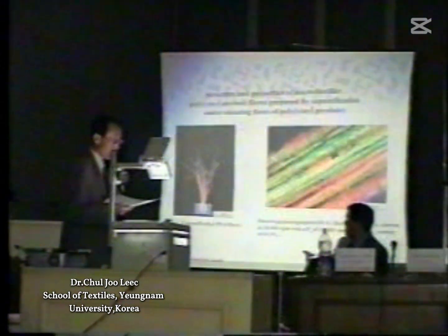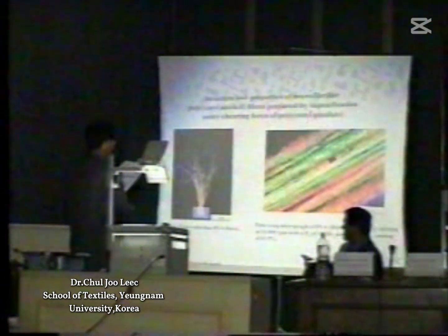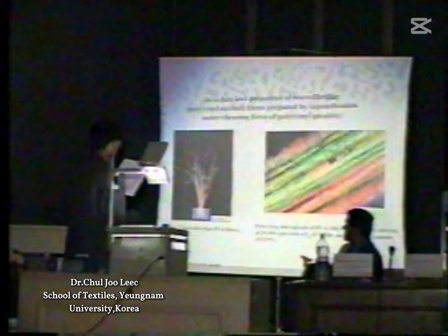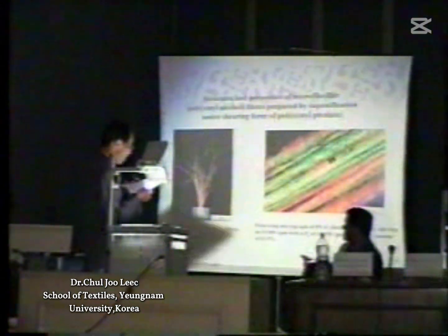I think many of you are now wondering what the fibrillars are. So these are photographs of our polyvinyl alcohol microfibrillars. The individual fibrillars are 1 to 50 microns in diameter and 0.5 to 200 millimeters in length. And they have an irregular cross-section and needle point-like ends. Their crystallinity is over 48%, and the crystal melting temperature is higher than 260 degrees Celsius. This picture is the polarized micrograph of one individual fibril.